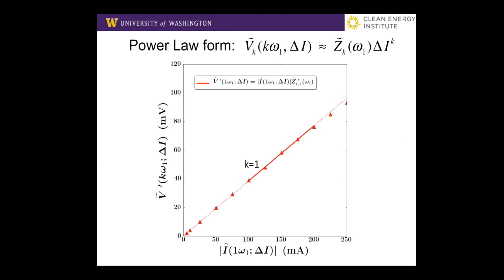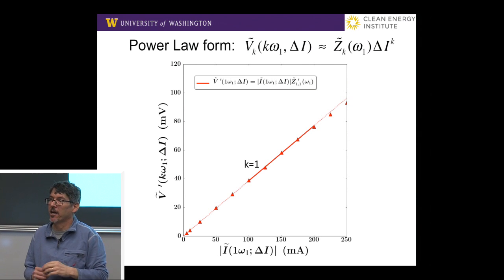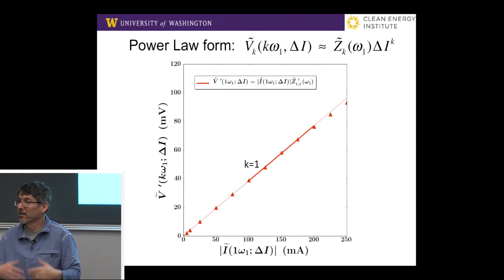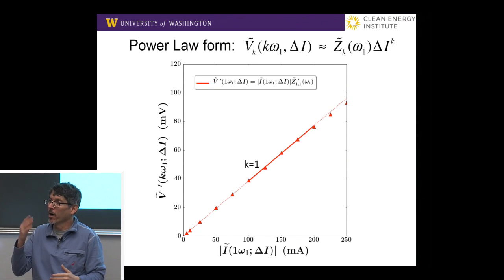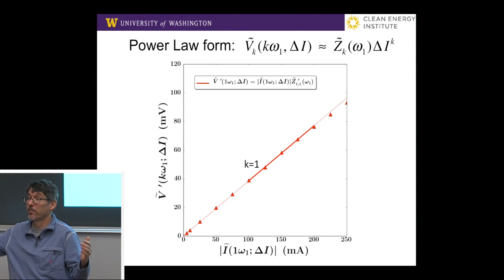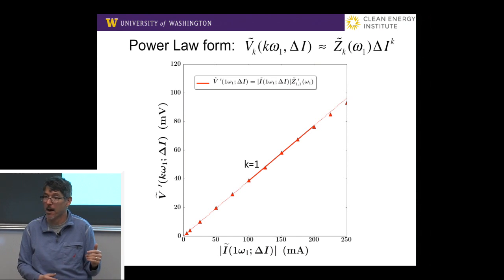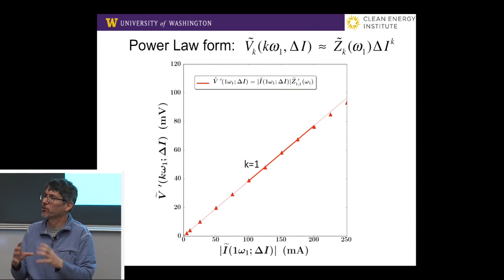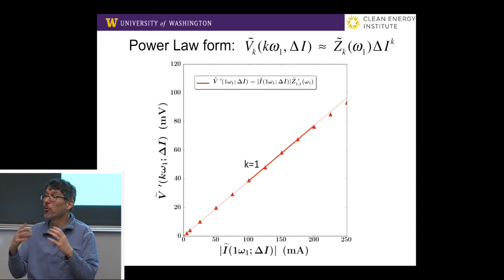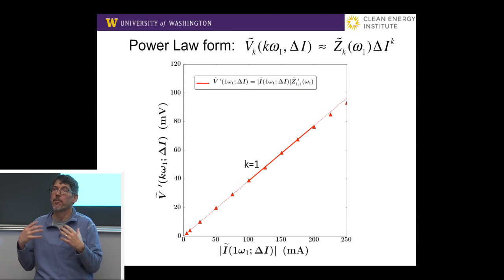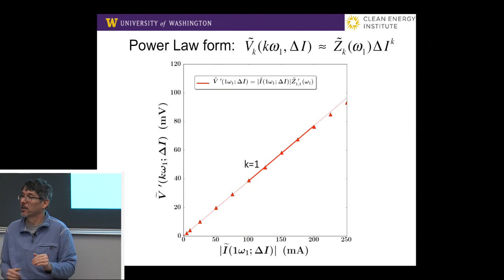If we look at the first harmonic, K equals 1, and this is the amplitude of the current modulation. This happens to be the real component of the voltage response. There would be a similar one for the imaginary. They follow power law type relationships. This is kind of akin to the linear and the nonlinear susceptibilities in optics, where the polarizability has harmonics depending upon the amplitude of the field applied to the sample. This is a little different because that's a fundamental trait of matter, and this is a system parameter. But we can think about them in some of the same ways, and I'm going to show you some of the physics. There are some interesting parallels in the physics.